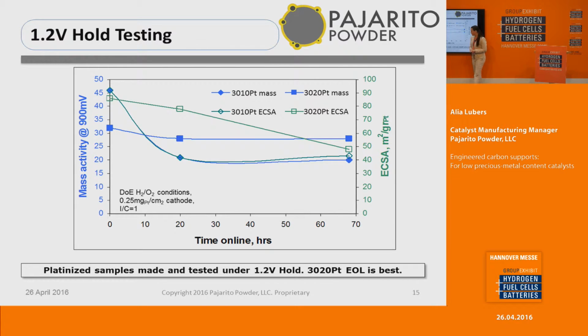The more graphitic material in the beginning has less mass activity, however, is more or less stable over the course of the test. So depending on your application, if you want a high mass activity in the beginning, a less graphitic support would be more advantageous. If you're looking for long lifetimes and keeping that platinum more stable, a more graphitic support would be more appropriate.